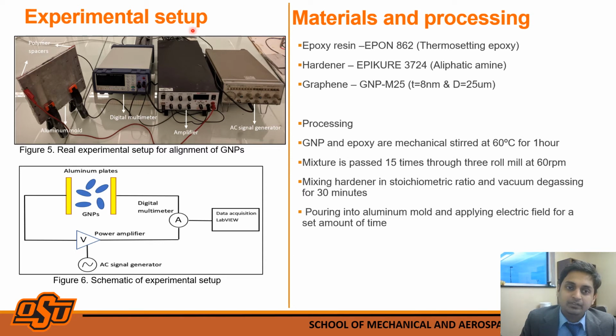To align GNPs, we created an experimental setup that can pass alternating current between two aluminum plates separated by polymer spacers to prevent shorting. These are connected in series with a digital multimeter, an amplifier, and an AC signal generator. The schematic is shown in figure 6. These are the aluminum plates, and in between there are graphene nanoplatelets, connected to the digital multimeter, which acquires data through LabVIEW software for AC conductivity, and it is connected to a power amplifier, which is connected to the AC signal generator, which provides the AC signal.